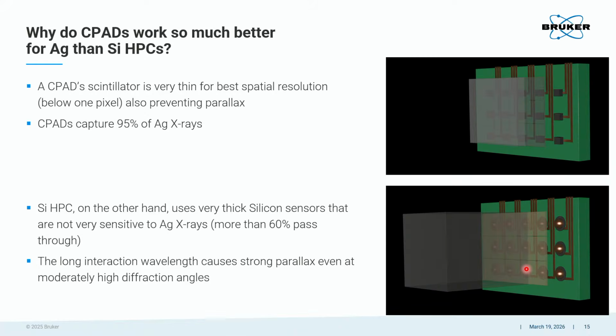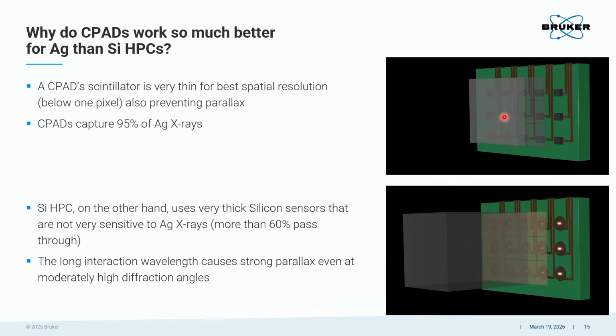And then a good point spread function doesn't exist anymore because you smear out your sample, and you can never recover that loss of information. That's just another form of noise. The nice thing, if you have a high Z scintillator, is that it doesn't matter at what angle you come in. The signal will be produced in the first few micrometers, and then your point spread function is very low because it always produces a signal in that same pixel or spot.